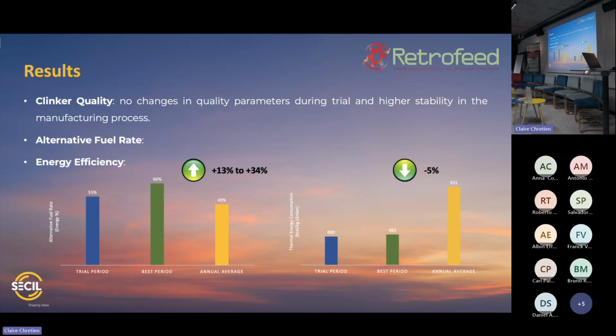So, of course, there is another piece of good news. There are no changes in clinker quality, because this could be a risk when you increase the substitution rate of alternative fuels a lot and so quickly. You may lose quality in the clinker. That was not the case. And we clearly see that we get a very high stability in the kiln and in the flame. So this is really promising for us.